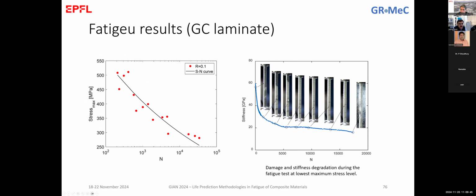And of course, this delamination propagates, so the stiffness drops more and more, and it comes now to the second stage of stiffness degradation, up to the final failure of the material. These photos were taken by the high-speed camera. So at the end, we have the final failure of the material due to this separation, if you like, of the layers at the end.